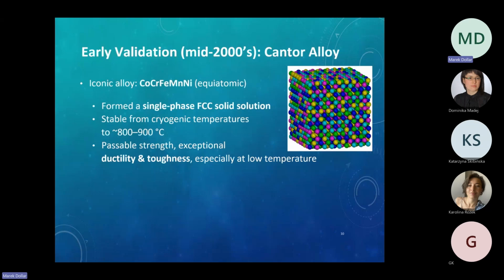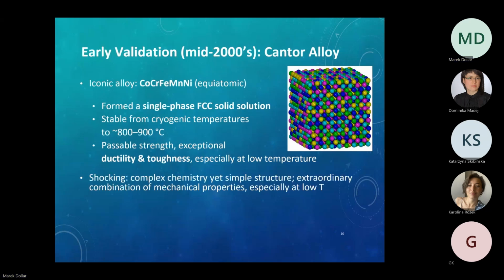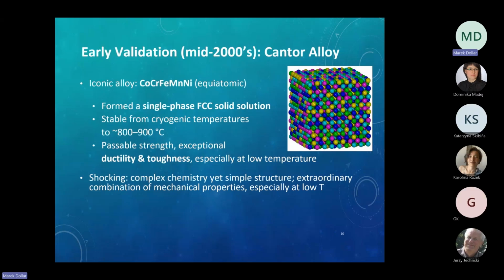This alloy wasn't particularly strong, but it had an exceptional combination of ductility and toughness. Again, especially at low temperature. So you could say, wow, there's a wow factor, if you will. Unusually complex chemistry, but very simple structure. And the alloy provides quite a combination of mechanical properties, especially at low temperature.